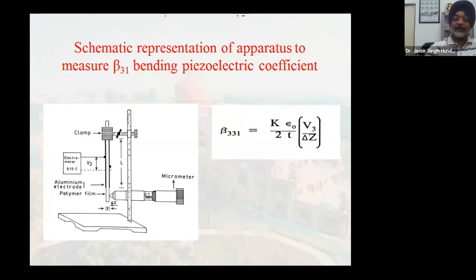Now here we have a micrometer. Here is the polymer film with the two metal electrodes on the two opposite sides, this surface and the other surface. This is the polymer film, which is connected to electrometer. We use the Keithley electrometer there. And then the film is held clamped at this place. But this end of the film is free. Here T is the thickness of the film. Okay. Delta Z is the deflection which we are able to produce with the help of the micrometer.